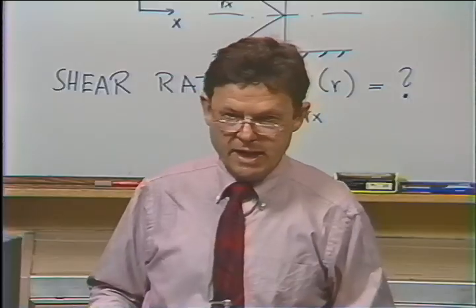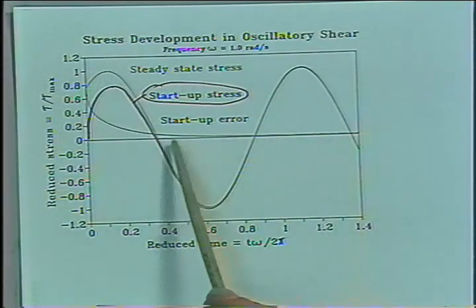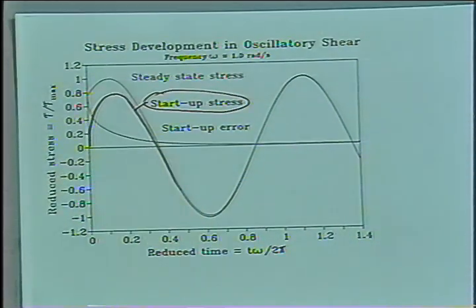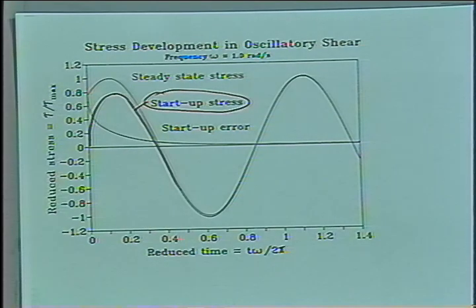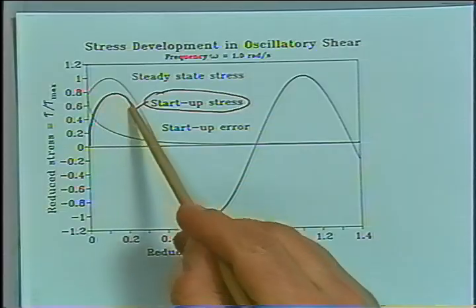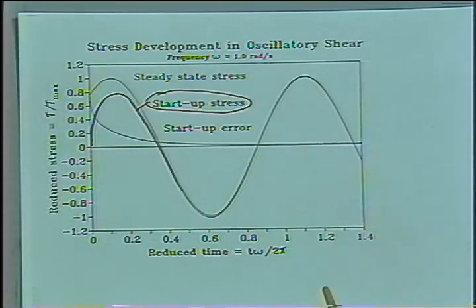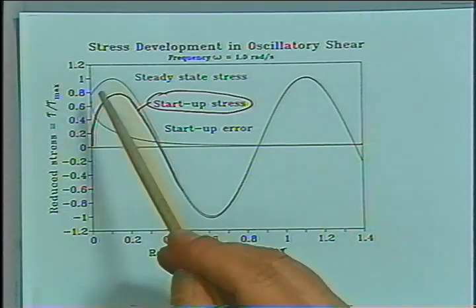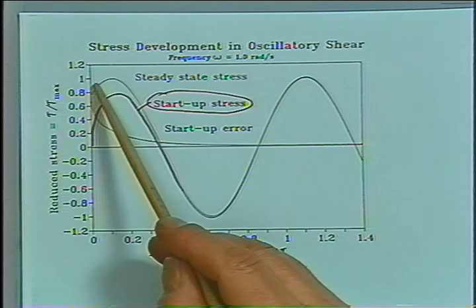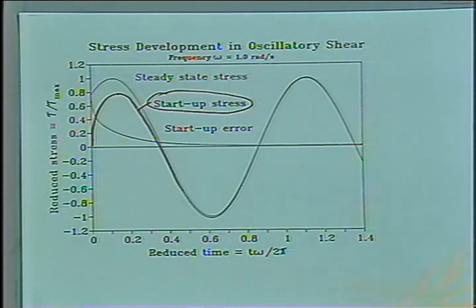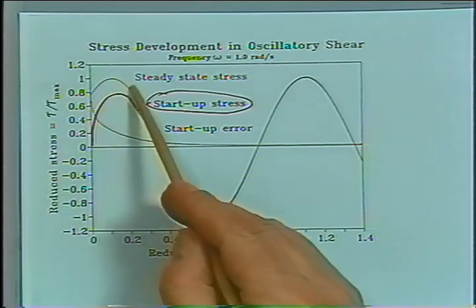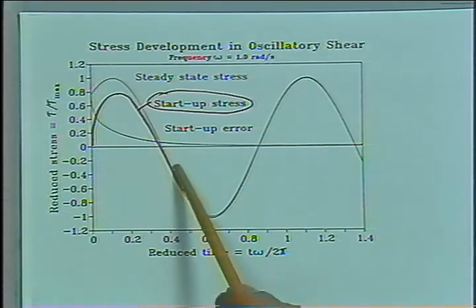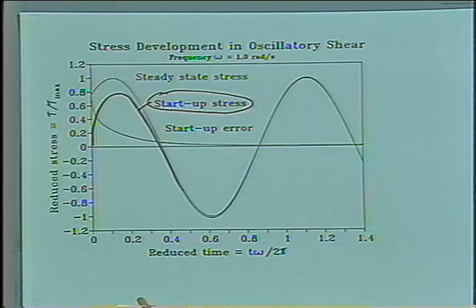The startup of that dynamic mechanical experiment is also interesting. We would like to probe our material on the time scale of a period, say, of our prescribed strain. Now here we modeled the startup of the stress as a response of the strain. And the stress really goes from 0 into some periodic function as a response of our prescribed strain. And we compare that startup of the stress to a calculated stress which would be found on a sample which was sheared oscillatory for a long, long time. So this sample would be in steady state, and you can see that the stress merges into the quasi-steady state in about one period of that experiment.